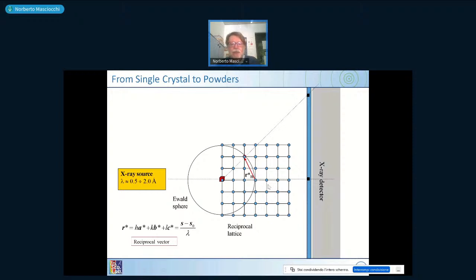But there are only a few spots. There's another one down here, another one down here, which are on this condition. And so that means if you take a single crystal, you may usually observe only a few spots, not enough information. But if you rotate the crystal, you see the crystal rotating in the center, automatically also what is called the reciprocal lattice starts rotating. And so you put into condition of reflection many other points which are entering and exiting the Ewald sphere, and then by rotating them, you have the appearance of many points on the screen, and you can basically sample all the points in your space, and all points together make the ingredients to solve and determine the structure.